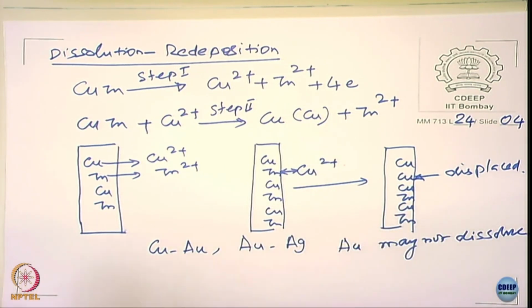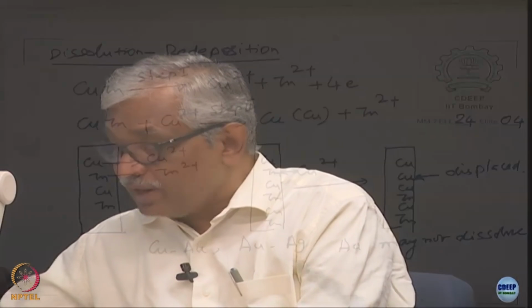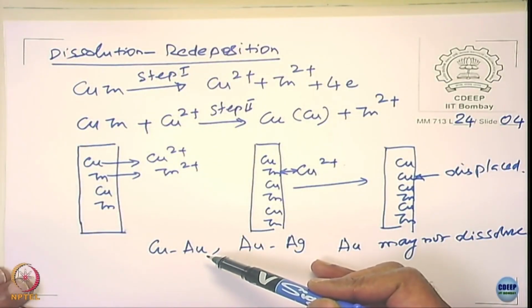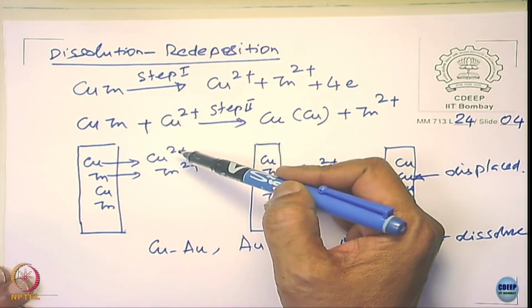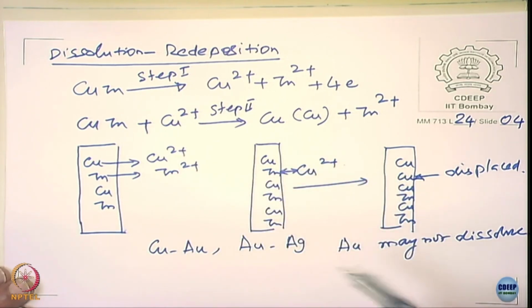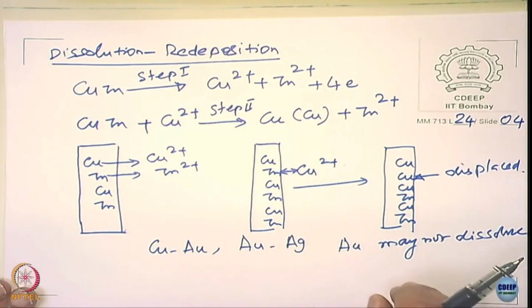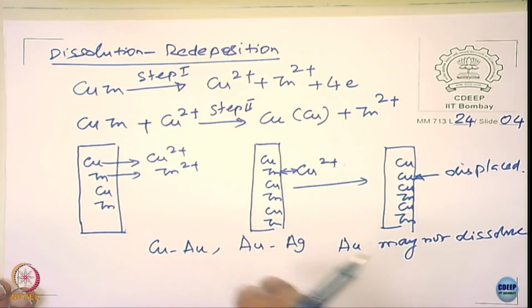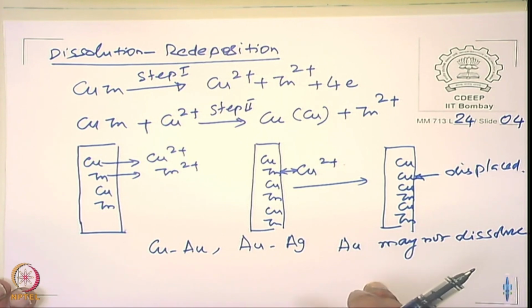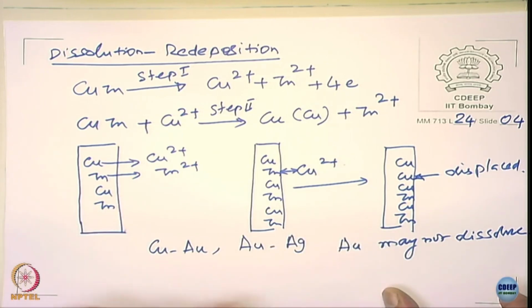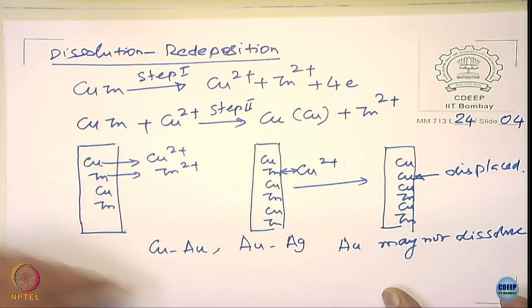Suppose I give you a copper gold alloy system and put it in an environment, not necessarily that the gold dissolves, like you have copper dissolution in the brass system, because gold is noble in this case. So without dissolution of the noble metal, it is possible only the active metal can dissolve, right? So in this case what happens now? It is saying it talks about the dissolution of only the active metal, the noble metal need not dissolve from the surface, okay. So it is really a selective dissolution and not a redeposition process. Do you understand the thing now? So this mechanism may not be valid in a system like that.